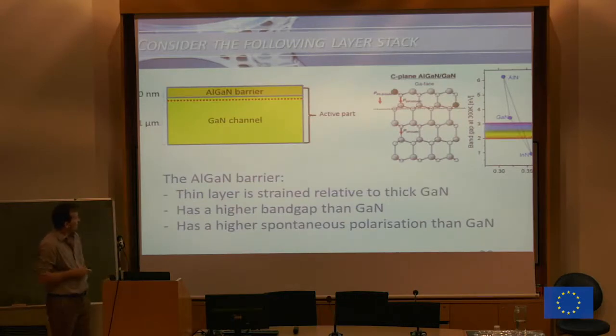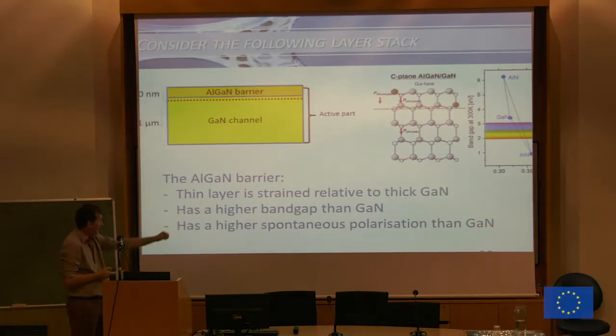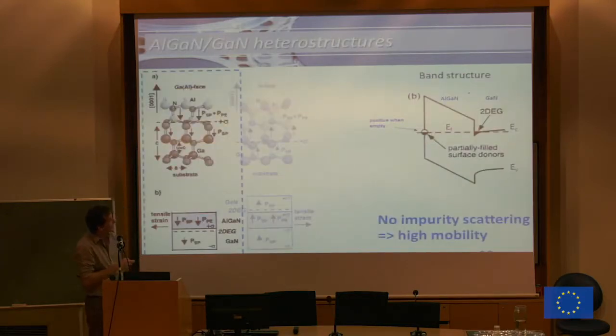So if you put that all together, imagine you have a very thick gallium nitride layer, and you grow on top a very thin aluminium gallium nitride barrier that has a strain relative to the gallium nitride, a higher bandgap, and a higher spontaneous polarization. You create a picture like this, and your bandgap diagram will have this bending because of the polarization effects. You have the bandgap offset, and you create this quantum well there. Very important is that you create this quantum well without any impurity doping. So there are no scattering sources for your electrons. So the mobility in the structure is naturally very high. Values were named yesterday. 2000 is, I guess, a very relevant number there.